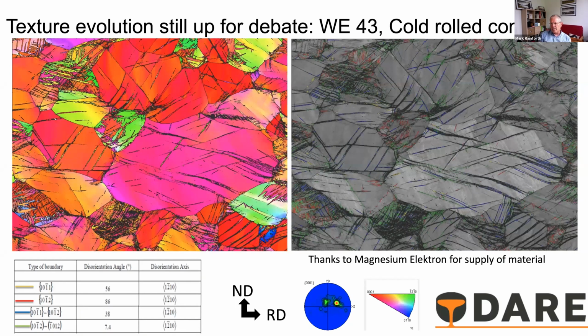Now, I won't go into this in detail, although again, I wish I could, but understanding that texture and why it evolves in magnesium alloys is something that is of interest. It's also quite controversial. These EBSD images show where some deformation has been put in, and we get extensive twinning in the structure. And there are different types of twins in there. We have compression twins, tension twins, and so on. So I say I won't go into the detail. But these play a very major role in developing this crystallographic texture.